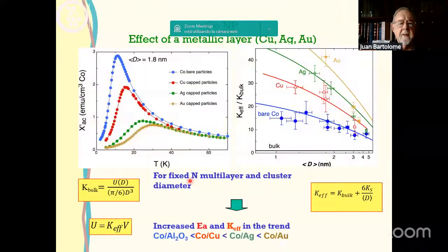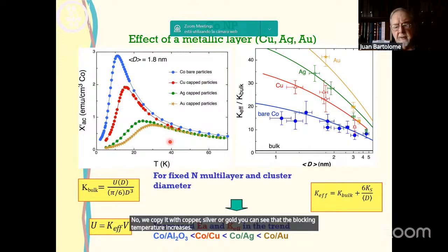So you see here the magnetic susceptibility of these cobalt particles for 1.8 nanometer diameter. The blocking temperature is relatively low, about 12 Kelvin. Now, as we cap it with copper, silver, or gold, you can see that the blocking temperature increases. We did also